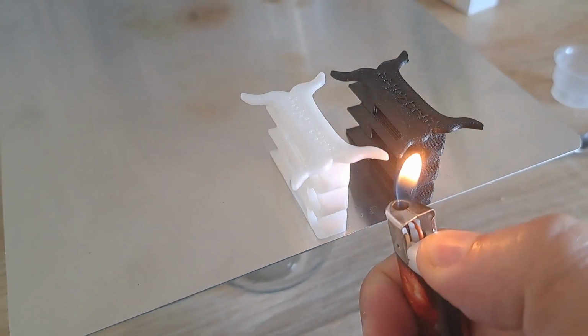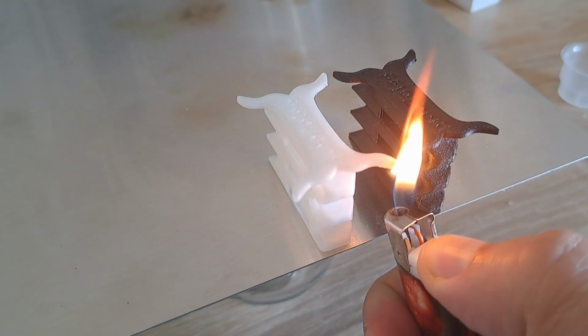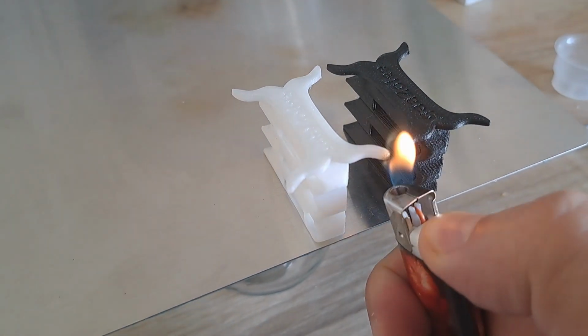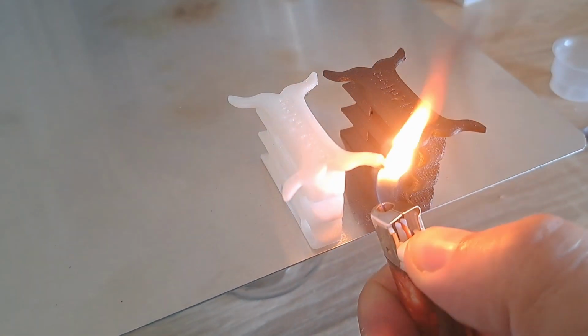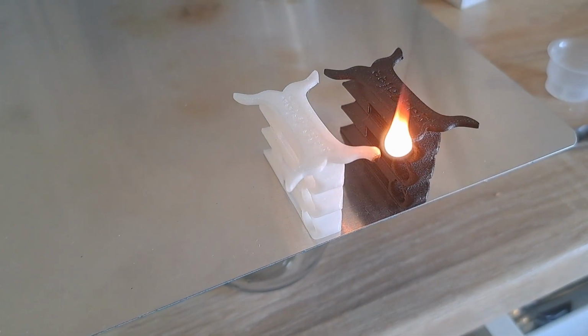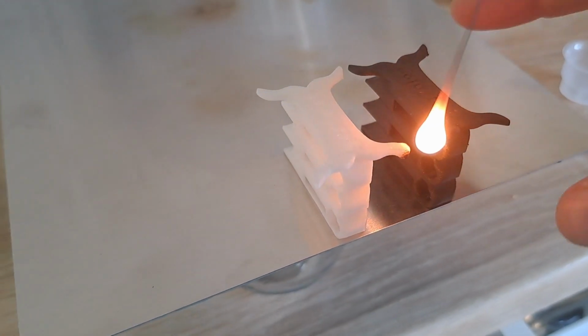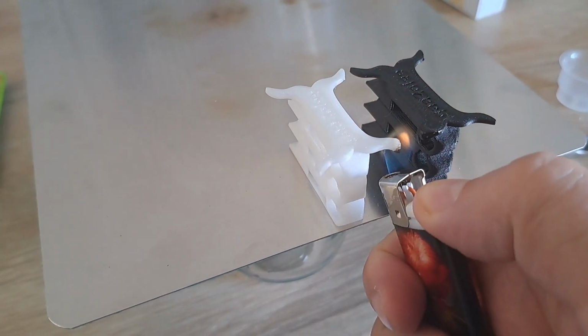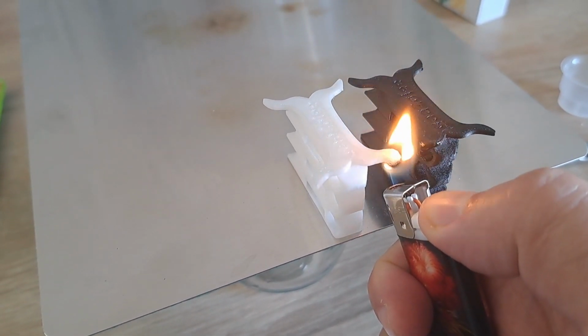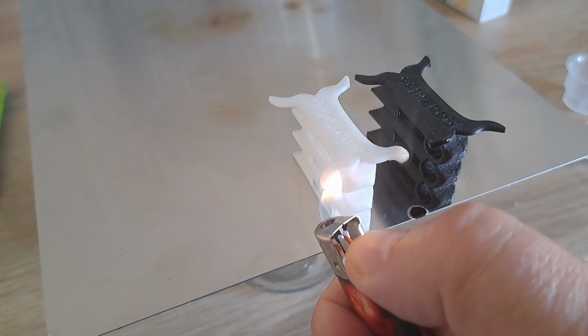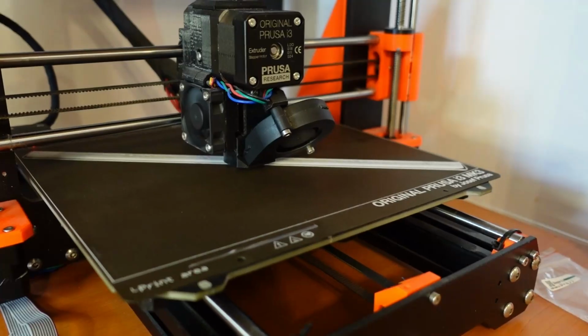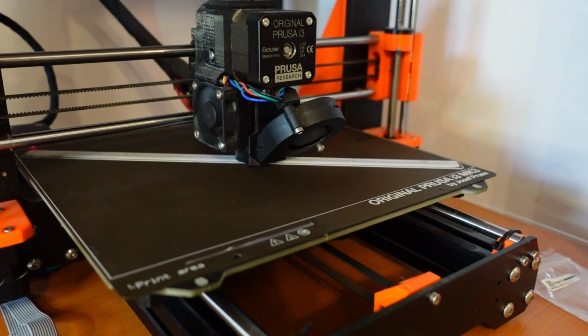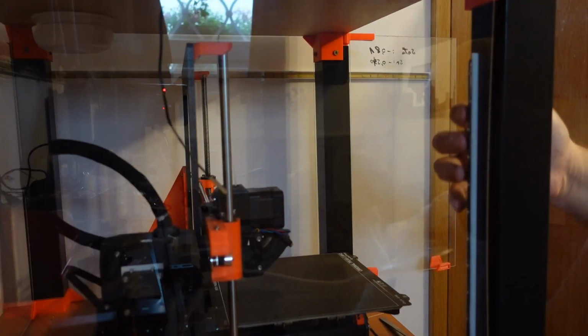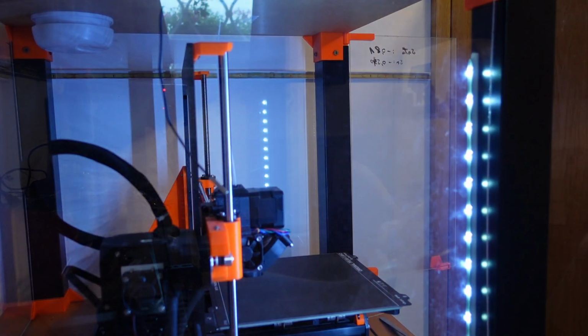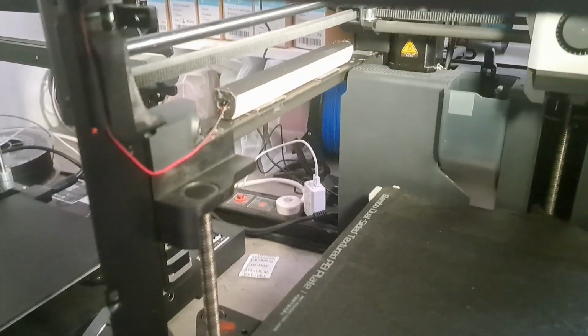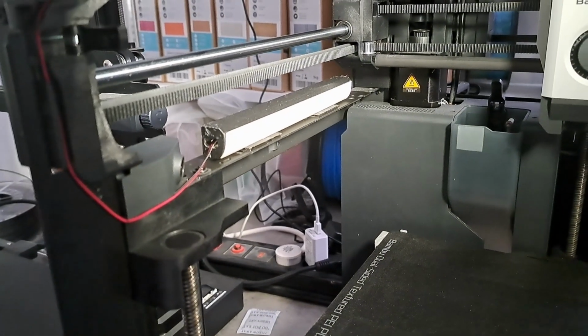And now the fire test side by side, V0 and the carbon fiber version, to check that self-extinguishing function of the V0. And yes, interesting, I didn't know that it will burn. The CF version catches the flame, but however I tried, I couldn't get a flame with the V0 version. And I already have a practical application for this filament. It's an LED holder which will be placed inside the enclosure. And also this is an LED cover for the P1P.